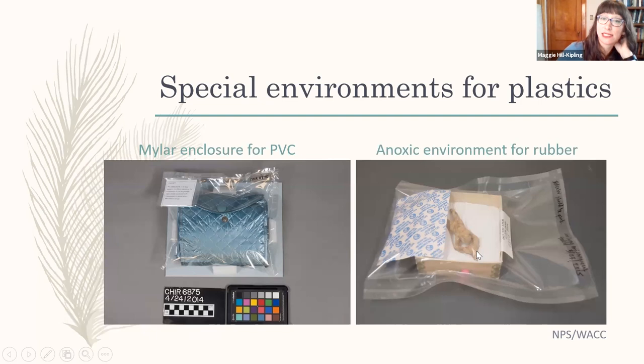On the right is a small little toy soldier from Manzanar. And that is a really interesting object. It was identified as potentially being guayule, which is a natural rubber that was actually produced at Manzanar during Japanese internment. And it was only produced for a short period of time there. So it's a really unique and interesting object. And we don't have a positive identification on it, but it appeared to be possibly a guayule object. So particularly important to preserve. And this was actually stored in an anoxic environment.